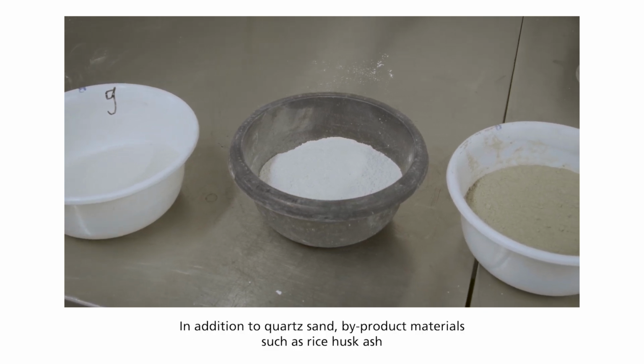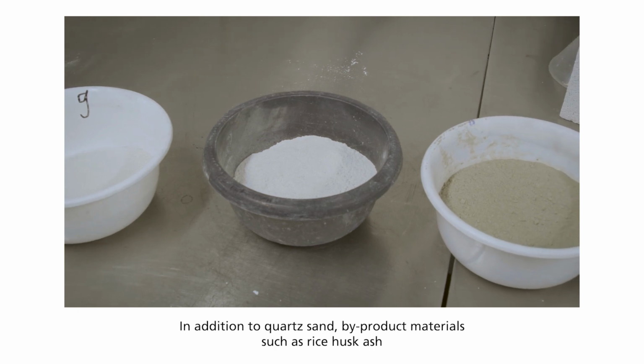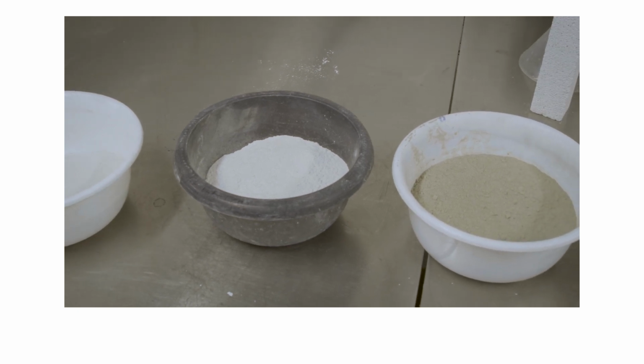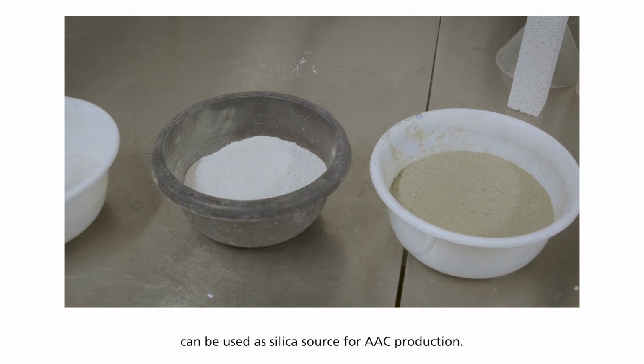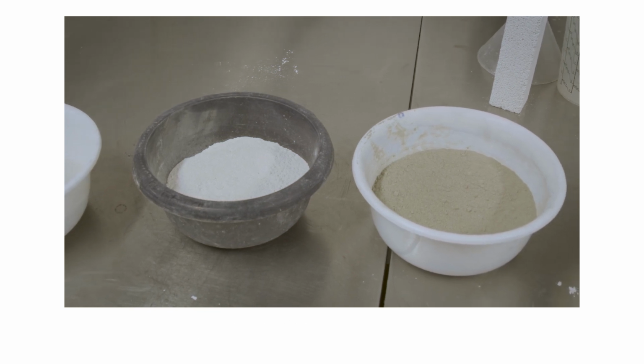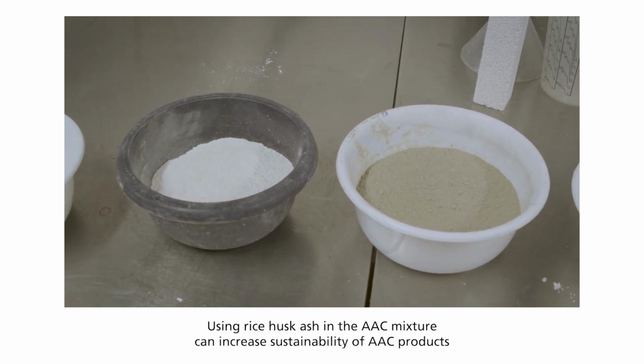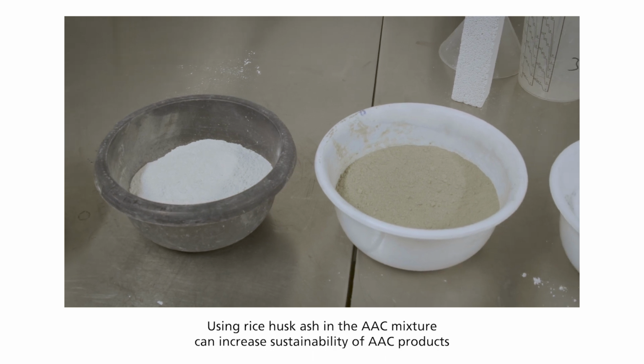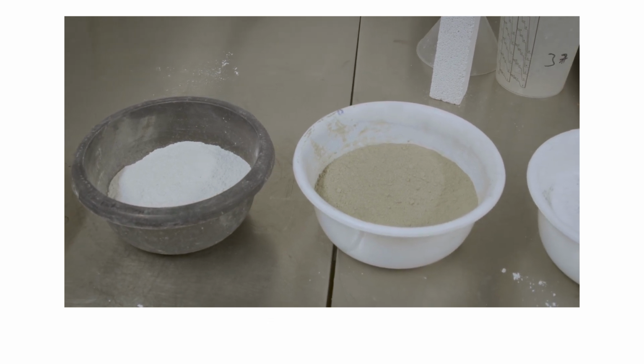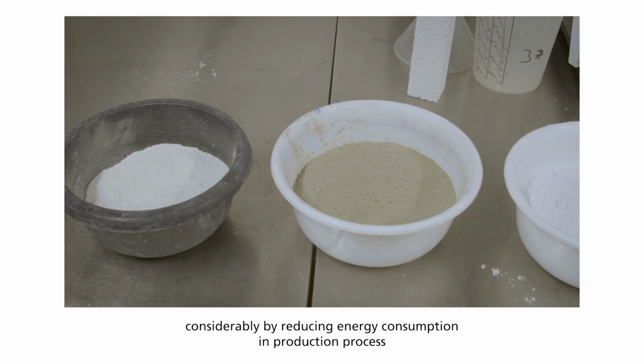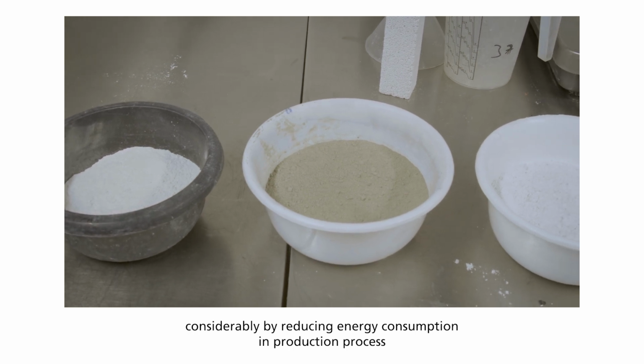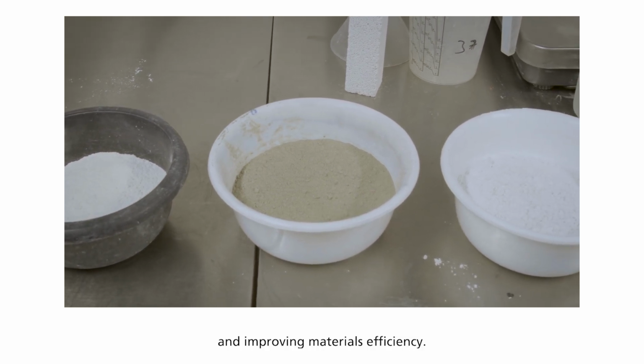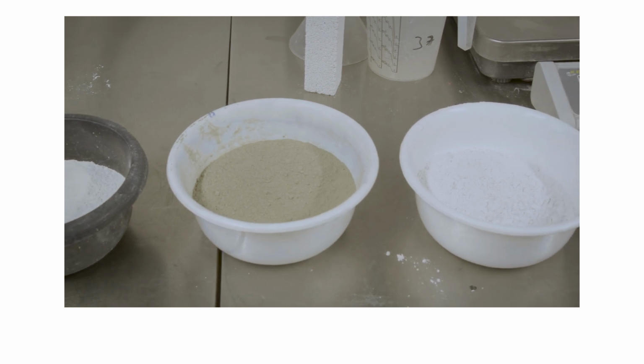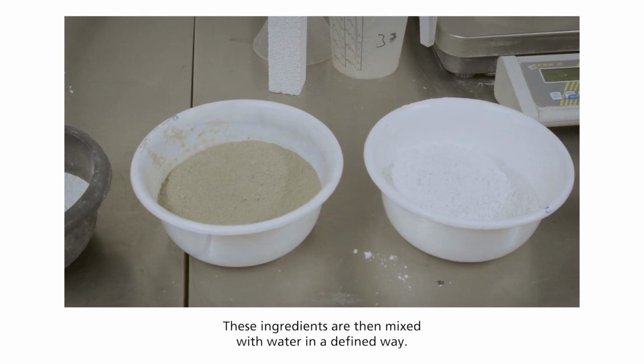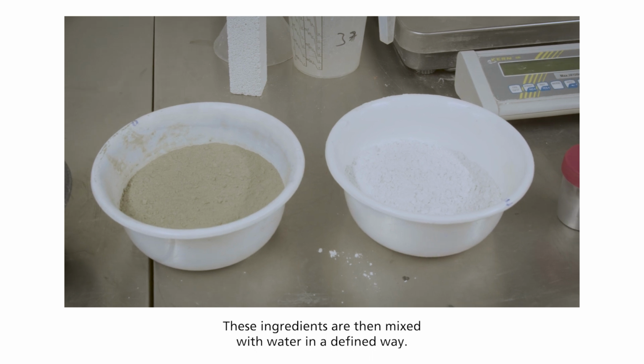In addition to quartz sand, byproduct materials such as rice husk ash can be used as a silica source for AAC production. Using rice husk ash in the AAC mixture can increase the sustainability of AAC products considerably by reducing energy consumption in the production process and improving materials efficiency. These ingredients are then mixed with water in a defined way.